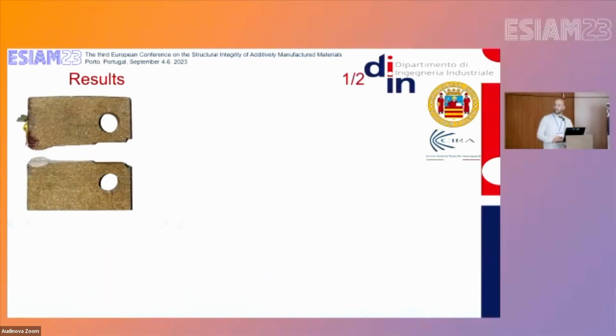So here we can see a figure of one of the fractured specimens. We can appreciate the typical mode 1 propagation. This was observed for all the specimens. This was rather expected, the specimen being loaded in pure mode 1.